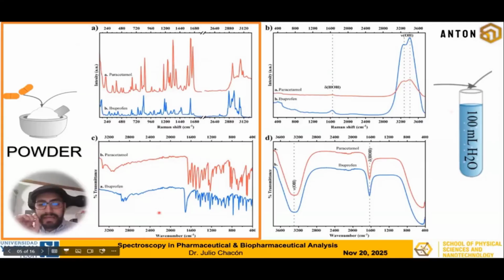However, if you take a tiny amount of those pharmaceuticals and you mix them in water, for example, 100 milliliters of water, then you will notice that when you measure this water in a Raman spectrometer, you will see absolutely nothing but water. In principle, it's fine because the majority of that is water, so that makes sense. But if you think about it, I took a tiny amount of paracetamol, a tiny amount of ibuprofen, diluted it in water, mixed it, and then you don't know that it's there because to our eyes, it's invisible. And also to the spectrometer, it's invisible, but it is there. I put it there, so I cannot lie.